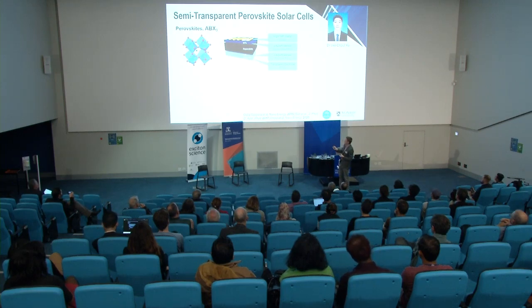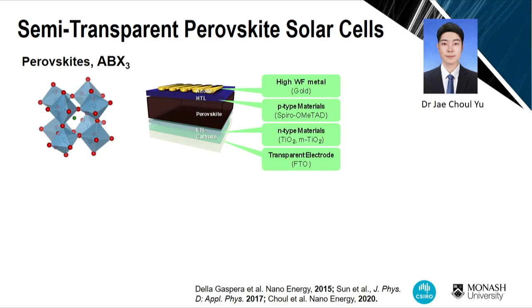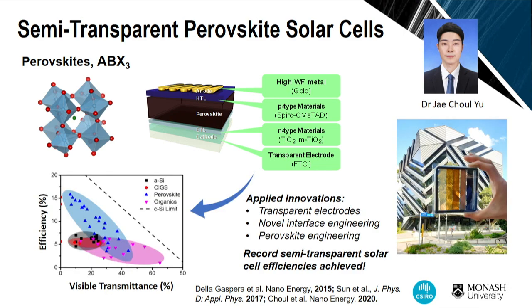So this is how a solar cell looks. This is a perovskite cell. I'm not going to be talking too much detail. It's a multi-layered structure, right? Like a sandwich, okay? And what we're doing here is we're optimizing the electrodes. So the electrodes have to be transmissive to light, right? We're optimizing the actual interfaces across each of these layers, and we're changing the composition of that perovskite. And again, Anita showed that variability in perovskite composition can give you widely different properties, okay? So by doing all of these innovations, we're starting to play around with exactly those parameters that we're trying to achieve. High efficiency, right, at high light transmittance, okay?